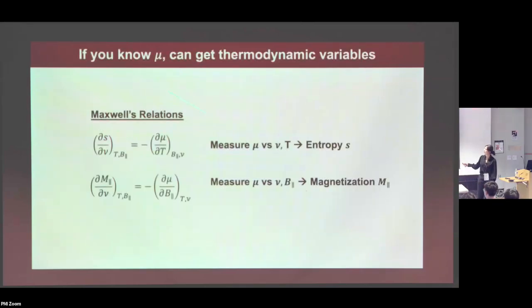And today I want to first talk about how we can measure this chemical potential, this water level itself. Another motivation for learning this chemical potential is that once you have the chemical potential as a function of other variables, you can also get other thermodynamic quantities. For example, if you know it as a function of temperature, you can know entropy. If you know it as a function of magnetic field, you can also obtain the magnetization from these measurements through our good old Maxwell's relations.